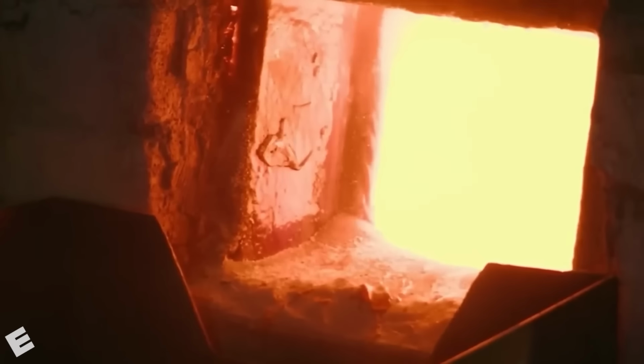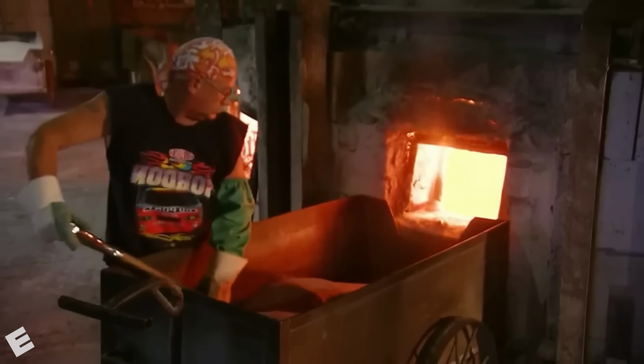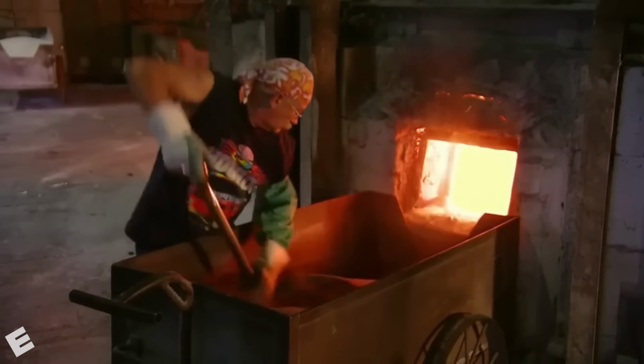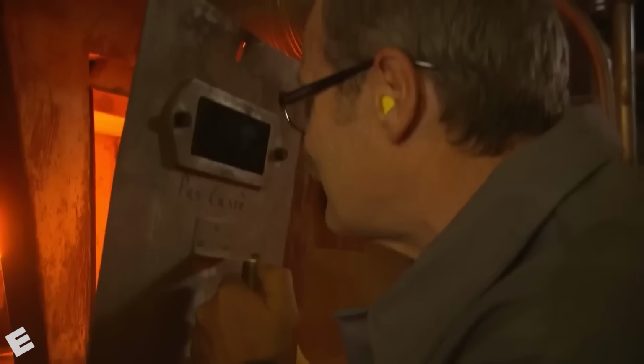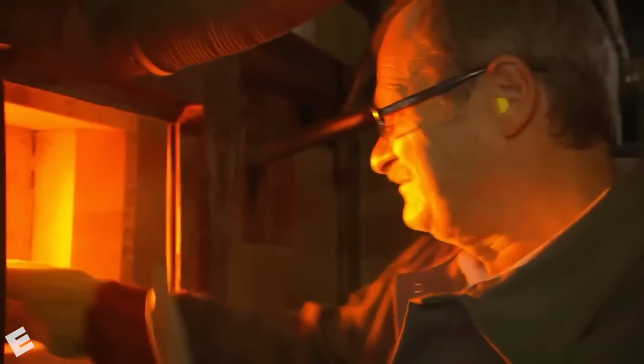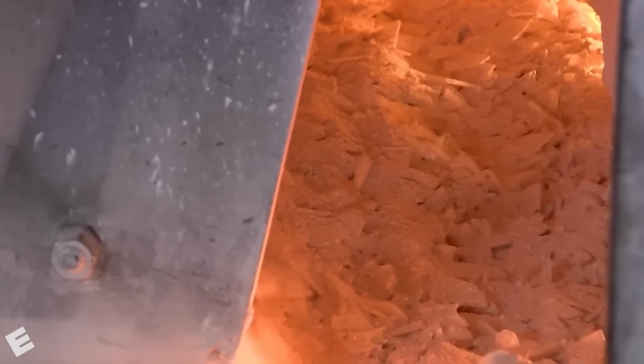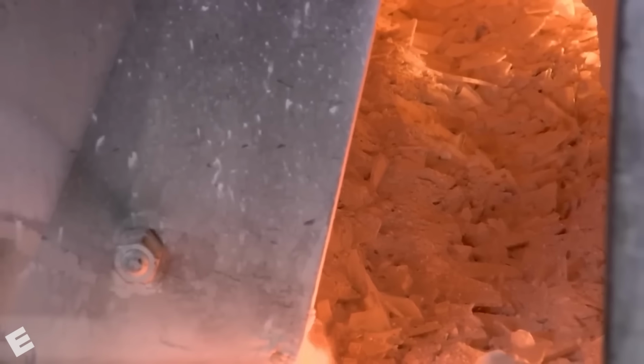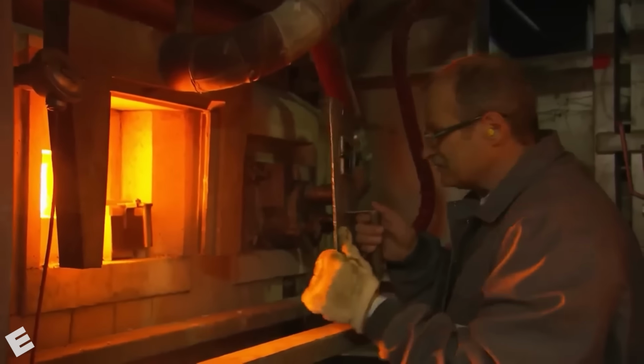to an astonishing 3,000 degrees Fahrenheit, about 1,650 degrees Celsius, far hotter than molten lava. At this stage, the furnace operator takes control. The mixture is carefully loaded into one of the furnace crucibles. Once everything is in place, the opening is sealed to maintain precise control over both the temperature and the melting process. Inside the plant, workers must wear fire-resistant suits along with heavy-duty Kevlar gloves.